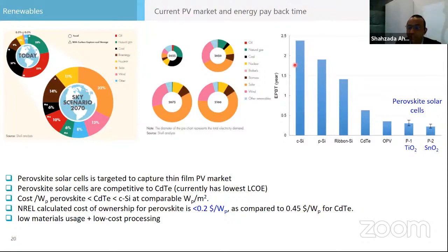So the energy payback time of crystalline silicon is higher, because silicon you need to heat, and you need silicon at 99.9999% purity. And to make it that pure, you need to heat it at 1200 degrees centigrade to make it semiconductor grade. That's why this escalates the energy payback time.